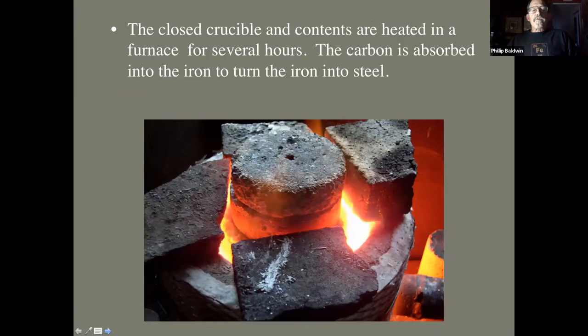Put it into a gas furnace, basically a melting furnace. And it says for several hours. What I found was an orange to a yellow heat, which is probably about 2000 degrees, in a mullite crucible packed with charcoal. We're talking about a 4-inch, 4.5-inch wide crucible at the mouth. For an hour to an hour and a half is going to be more than sufficient to create a very hard carbon steel. You've got to remember the thickness of the strip that you start out with is going to be important. The thinner the strip, the faster it's going to carburize. Pretty straightforward.